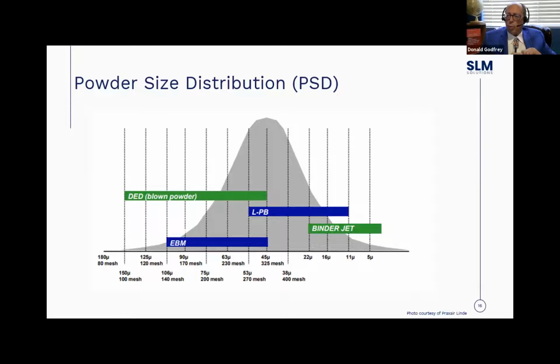With powder, you can hold a dimension plus or minus 5 thousandths. With DED, it's going to be plus or minus 25 thousandths. It's a huge delta. So you use DED for speed, that's going to be machined down later. You use powder bed for fidelity. So for example, if you're doing a gearbox with oil passages, you would never use DED because the oil passages would just be a disaster. But with powder, you can print that. Okay. Thank you, Don. Sure.